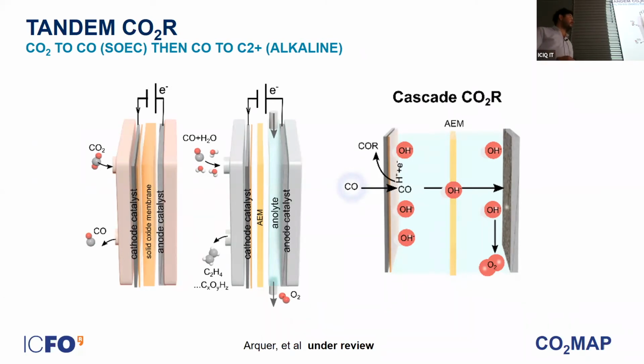So in order to overcome actually for good this carbonate formation problem, there are different strategies. One strategy is just, okay, to separate the reactions. We know CO2 reacts with hydroxyl groups. What about we do the CO2 reaction to another product, such as CO, in a system that does not have the requirement for high alkalinity? And this is the case of the solid oxide electrolyzer. For example, there are systems such as this that operate at high temperatures and have very high Faraday efficiencies for CO. So you just have a first system where you generate CO, and then you could plug this CO into a second system, which could operate in alkaline conditions very well, and that wouldn't suffer from this kind of carbonate generation problem.